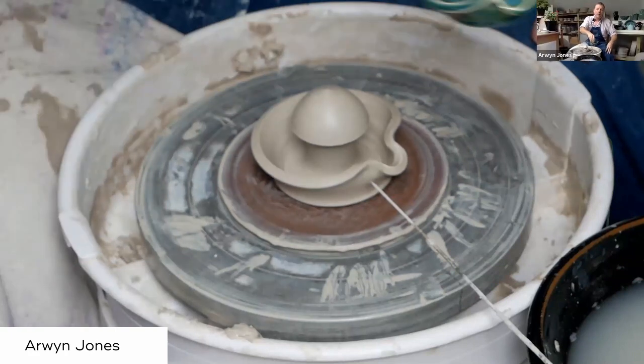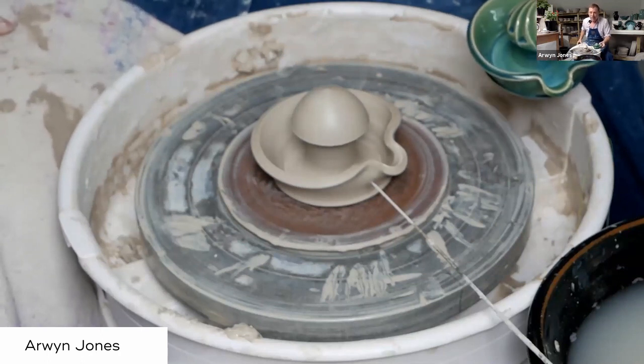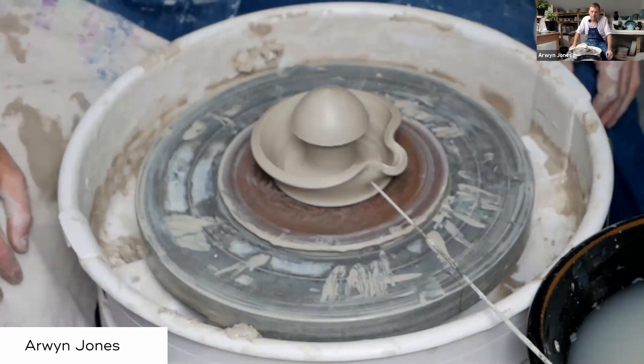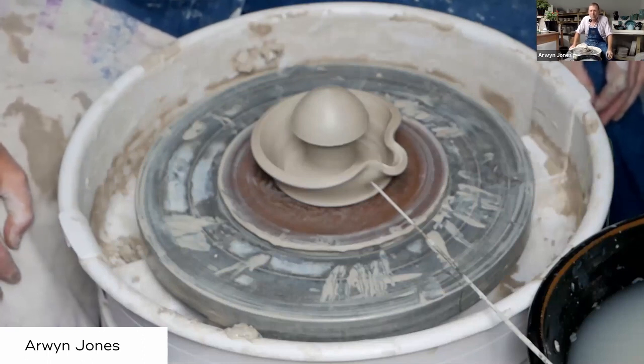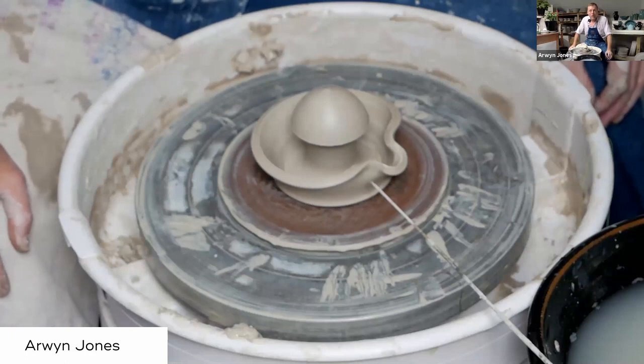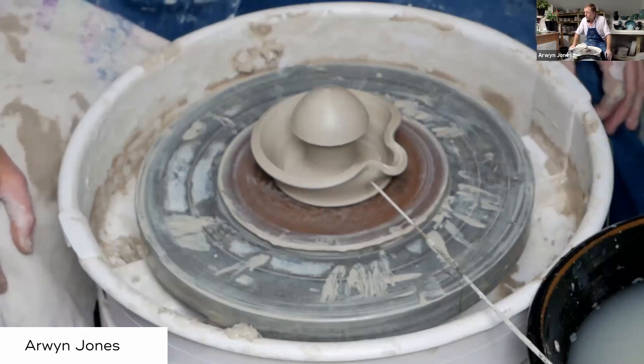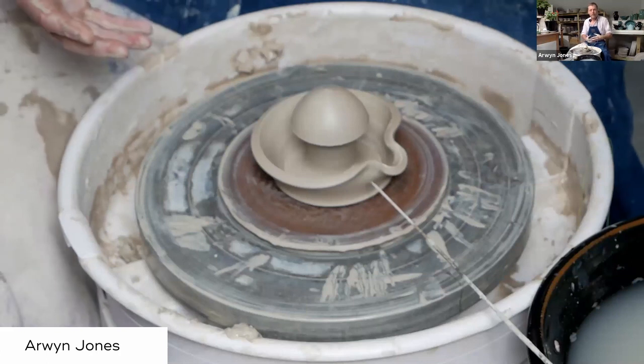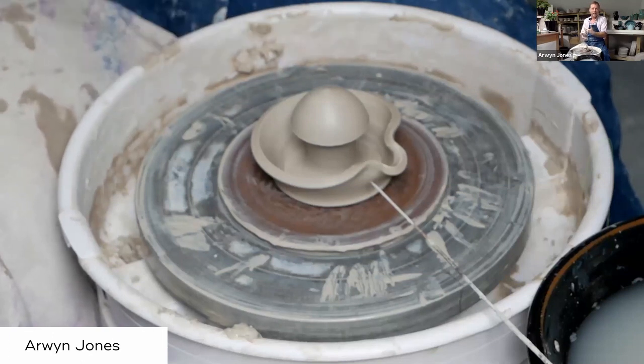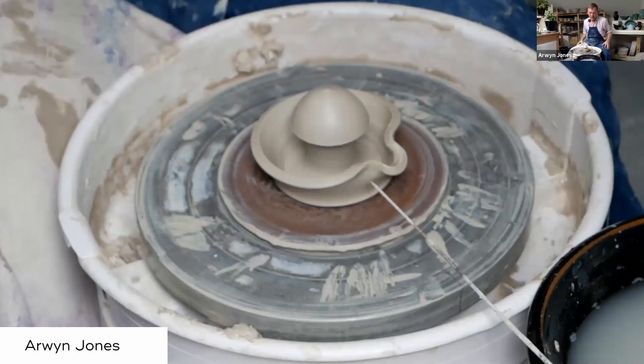Yeah. They may vary. I mean, that is the same green, but the materials that we use to make the glazes come out of the ground, so there will be some natural variation. Also, I'm now using a different kiln. I think it's probably the third or fourth kiln since I started, and they all fire differently, even though they're electric. This one is a lot bigger, so it gets hotter against the edges, the heat radiates, and inside it's a little bit cooler. Where it's cooler, there'll be more of the bluey green color. Where it gets hotter, it'll be more green because the crystals in the glaze have dissolved because of the heat to create that translucent glaze. What I'm trying to do is create that balance between something that's partially dissolved and something that hasn't, so it gives a nice depth to the pot.